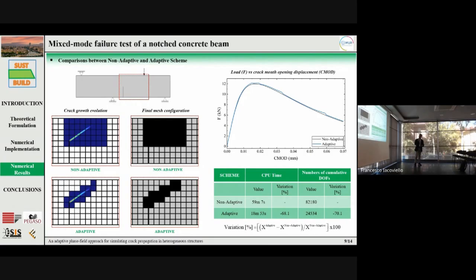Now, a comparison between non-adaptive and adaptive schemes is reported for evaluating the computational efficiency of the present method. Note that to reproduce the non-adaptive scheme, the microsubdomains are activated at the beginning of the simulation. This slide demonstrates the advantage of the adaptive scheme. In fact, the non-adaptive and adaptive curves for load versus crack mouth opening displacement are almost the same, and this denotes that the adaptive scheme does not compromise the accuracy of the simulation.